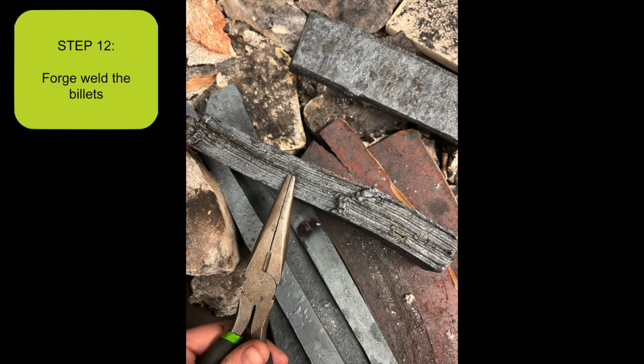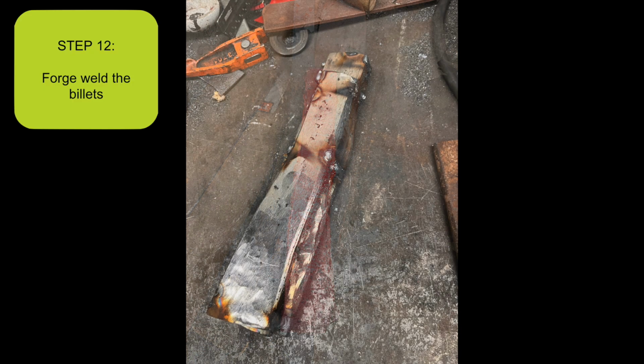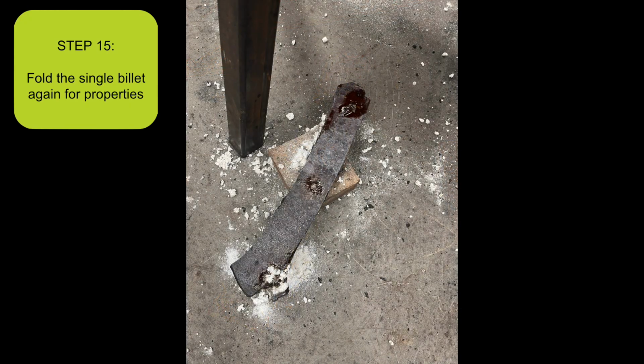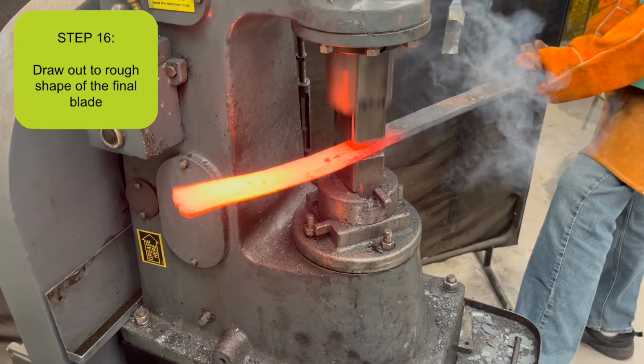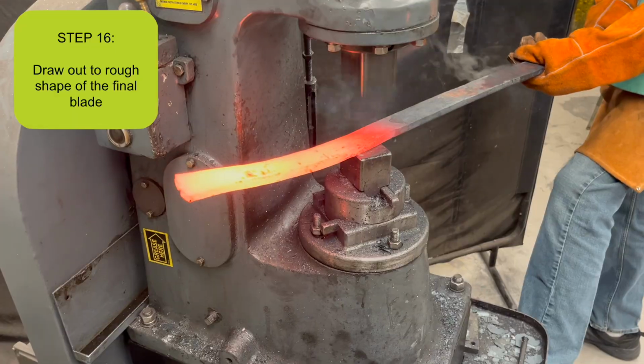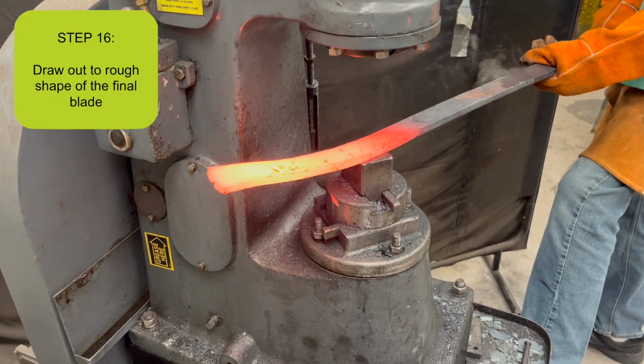Once the material was carburized and layered with 1095 in 2 billets, each billet was folded in half once before they were combined and folded one last time. The billet was then drawn out to the final length of the blade. Once it was long enough, the rough shape was put into the blade to prepare for heat treatment.